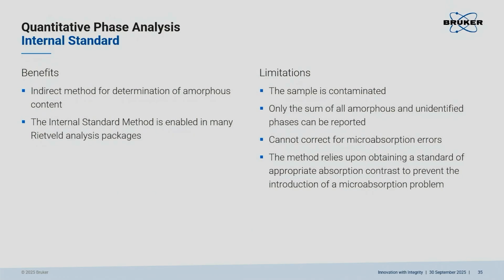So the internal standard method is an indirect method for determination of amorphous content. Remember, the amorphous content is something you cannot see by eye, where you cannot do a fit to obtain the amorphous content. If the sample is contaminated, it gives you only the sum of all amorphous content. That's also important to remember. You cannot correct for microabsorption errors.